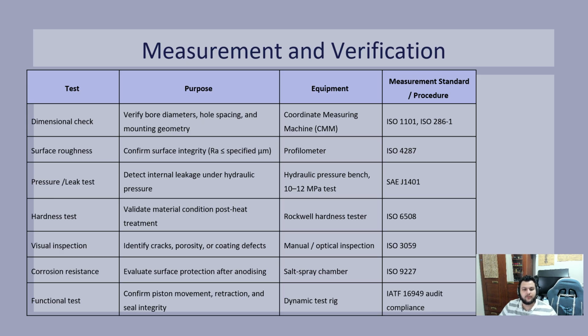Next, the surface roughness is assessed with a profilometer under ISO 4287, ensuring the required Ra value for sealing and wear control. The pressure leak test applies 10 to 12 megapascals of hydraulic pressure following SAE J1401 to verify the seal integrity. Hardness testing under ISO 6508 confirms the proper heat treatment of machined parts. Then visual inspections check for cracks and coating defects per ISO 3059, while the corrosion resistance test in the salt spray chamber complies with ISO 9227.